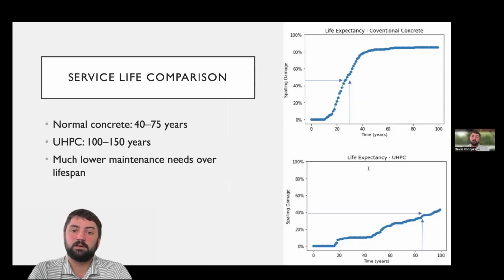Here we have a real service life comparison. The charts on the right will show deterioration trends from conventional concrete versus UHPC. Traditional concrete may start showing significant scaling damage at around 20 to 40 years, depending on the exposure, while UHPC maintains its integrity for far longer, typically projecting 100 to 150 years of service life. This is the moment where you really understand why owners are willing to pay more for UHPC up front, because you're trading a slightly higher material cost for essentially doubling the lifespan of the structure.